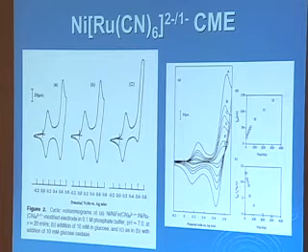Savéant plots, actually. Why do you need the ferrocyanide at all? If we make a nickel electrode without the ferrocyanide there, it's not stable towards corrosion. So it's an anti-corrosion coating. And it's very convenient that it's an internal standard. That's just extra. What we've done here is a standard plot of the peak current versus scan rate.